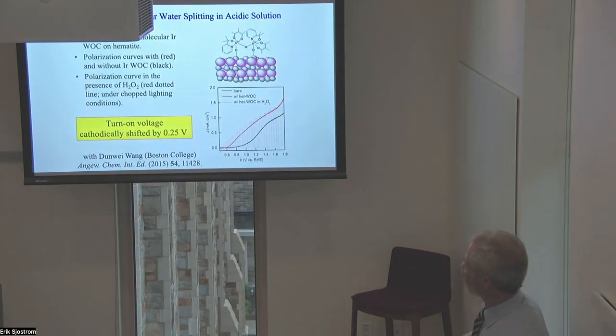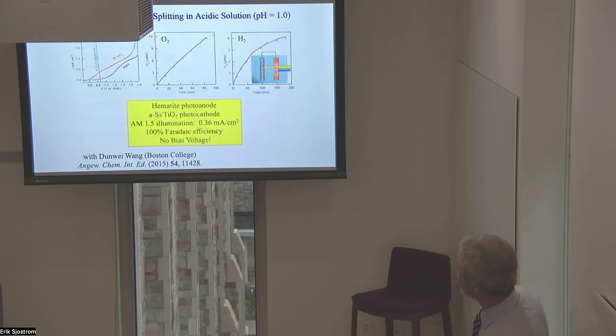And this is work that was done with Dunwei Wang. It was published quite a few years ago, putting it on hematite. And you can see that when it's bound to hematite, the photocurrent occurs at a lower potential, so it's improving the water photooxidation. It shifts by about 250 millivolts by binding this catalyst on the surface.